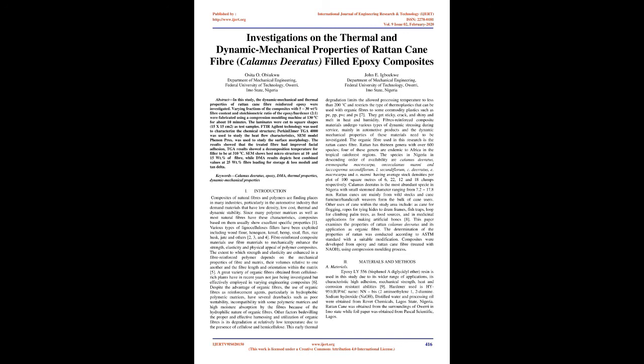Varying fractions of the composites, with 5 to 30 wt% fiber content and a stoichiometric ratio of the epoxy/hardener of 2:1, were fabricated using a compression molding machine at 130 °C for about 10 minutes. The laminates were cut to square shapes, 15 x 15 square centimeters, as test samples.